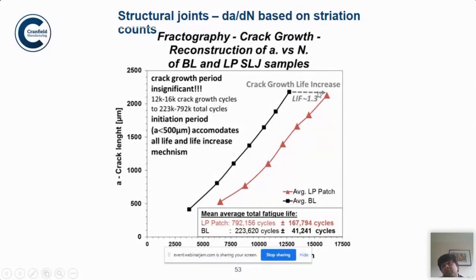Now these are life improvement factors. So there is always a question of how the life is improved. Whether the life is improved by reducing the crack propagation, or whether the life is improved by delaying the crack incubation or the crack initiation period. So you can see here the life improvement factor is about 1.3, or 30% life is improved when you have through extension and crack growth.